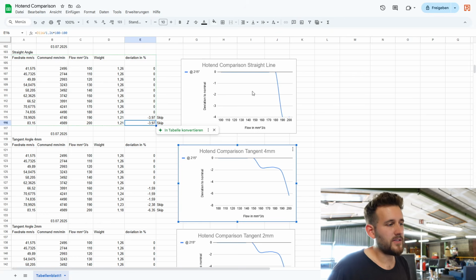And visually you can see that right about 150mm³/s flow rate, there is a difference you can actually see in the filament that is coming out. So the viscosity is changing, and therefore I guess 150 is absolutely safe where we're right now, and if we want to push it we can go straight up to like 180. But this is all being done at just 215 degrees on a high flow PLA from Fiberlogy and a 0.8mm nozzle.